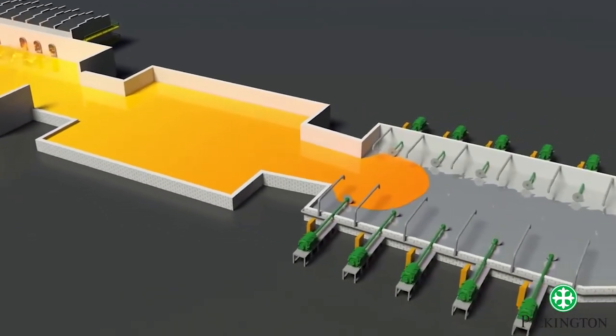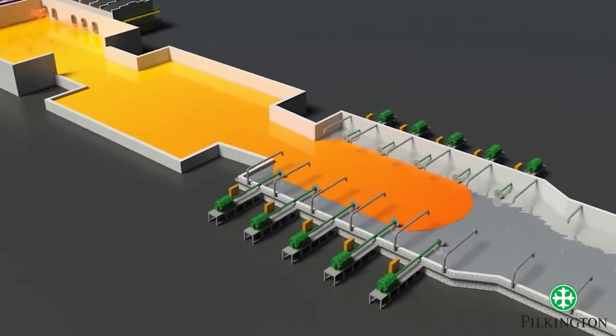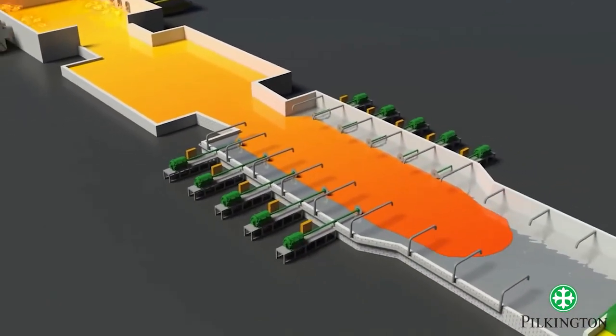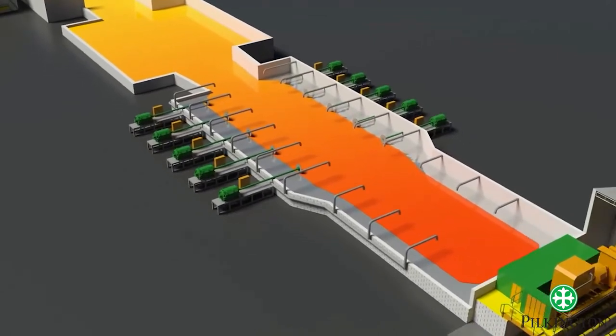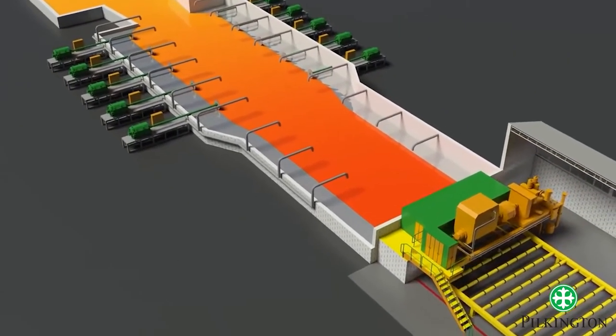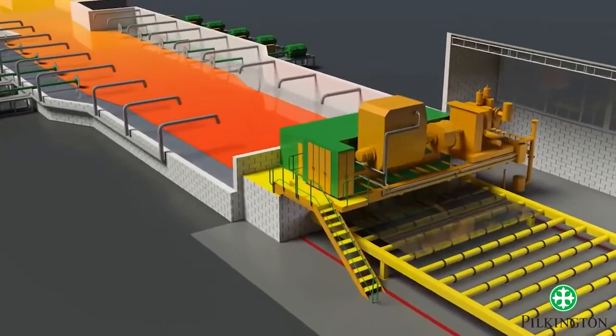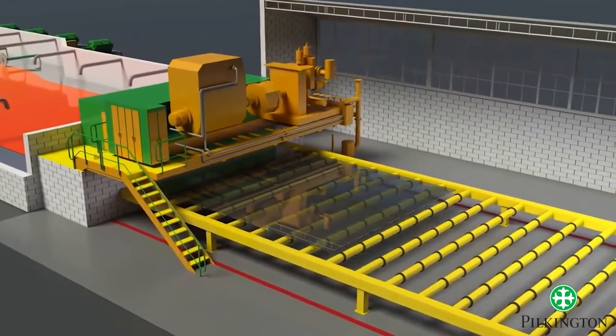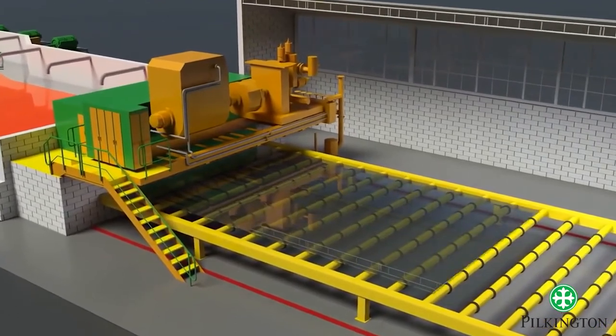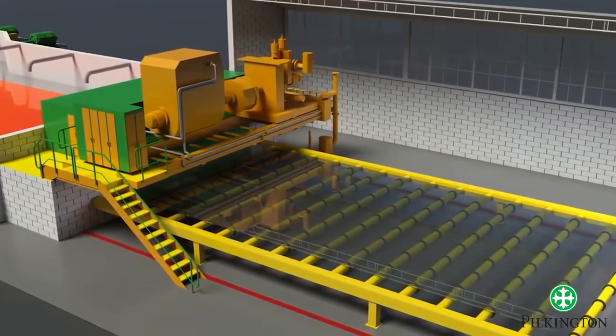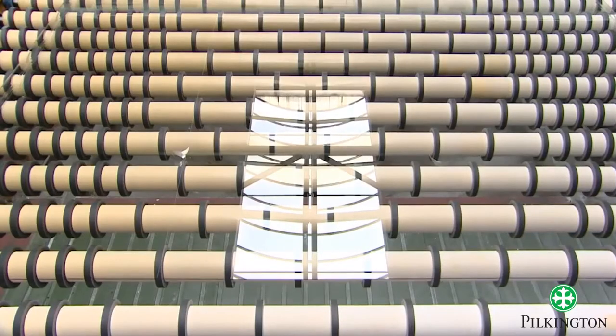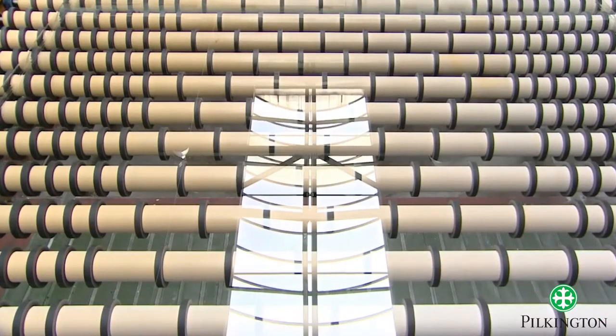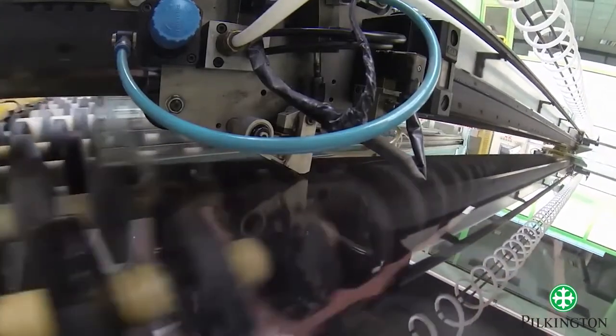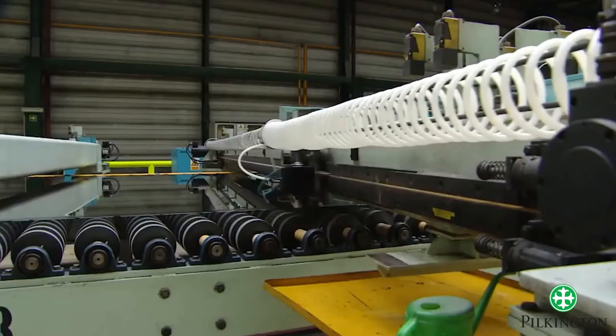Float glass is the molten glass, the materials are melted at the beginning of the line, sand, potash, silica, and it's an overflow tank. And so they melt so much of this raw glass that it overflows and they flow it over a liquid bed of tin. And since it goes on this liquid bed of tin, the tin is more dense than the glass, so the glass floats over that liquid bed of tin, continuously comes off in a continuous ribbon where it's slowly cooled and then cut at the end of the line. And a float plant runs 24 hours a day, 7 days a week. And every day a float plant produces about 700 tons of glass.